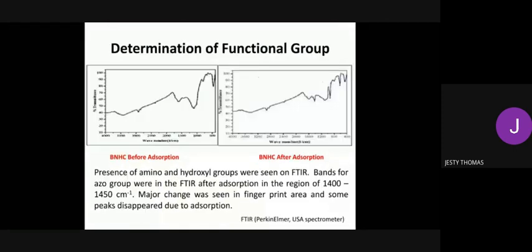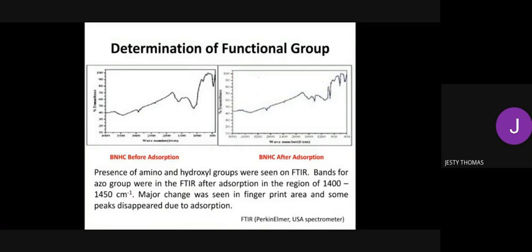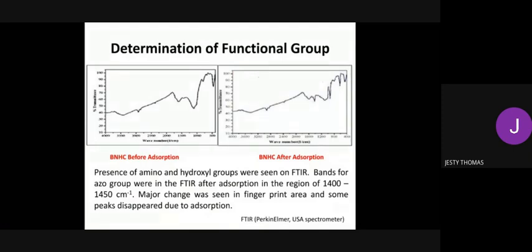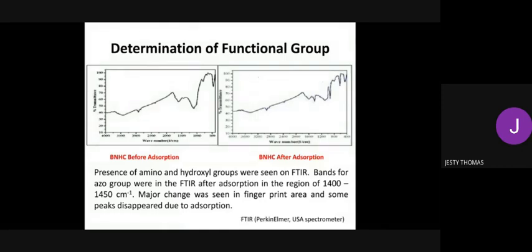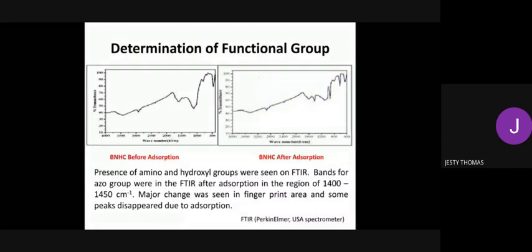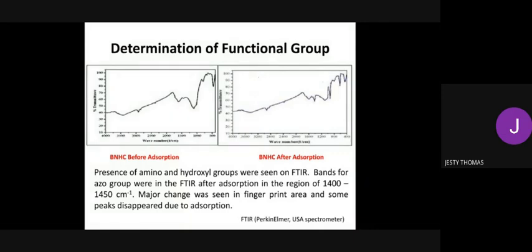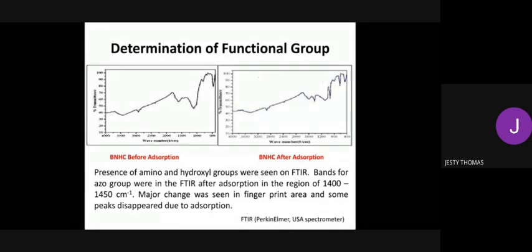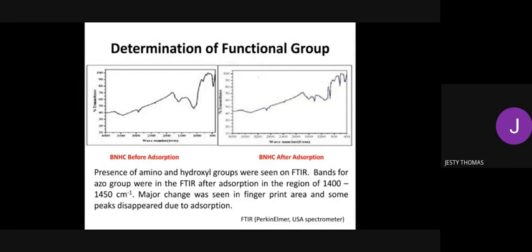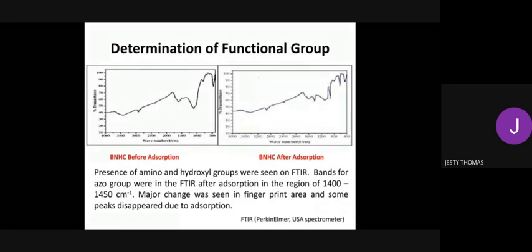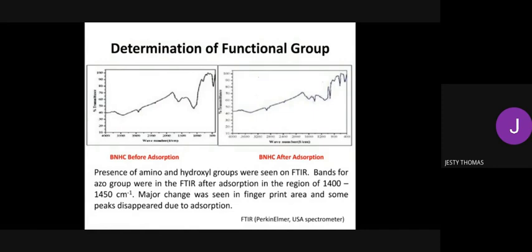Then we recorded the FTIR also. FTIR before and after adsorption showed some changes in the fingerprint region. There is no major change in the functional region of the IR, but in the FTIR after adsorption we noticed the azo functionality, that is the azo group of the dye, seen in the range of 1400 to 1450 per centimeter. This indicated that the dye is successfully adsorbed on the surface of the biosorbent. So these are some changes seen in the FTIR after the adsorption process.